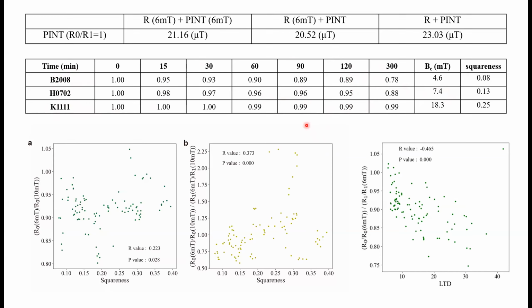And we also have some other evidence: if we use the full coercivity range to get the baseline regression, we will have an erroneous value of the paleointensity when its R before and after heating equals 1.